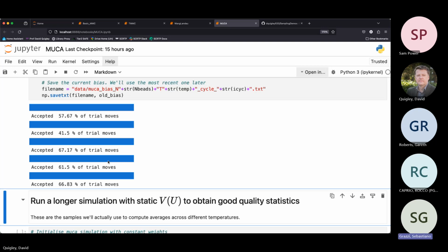multi-canonical sampling in the context of where I've got two energy modes separated by a very large barrier. And we do these phase switch methods. So we introduce a Monte Carlo move that we define our microstates relative to the minimum of the mode. And then we have a Monte Carlo move that just swaps the minimum. And you will never accept that move unless you do some multi-canonical bias to make you accept that move.